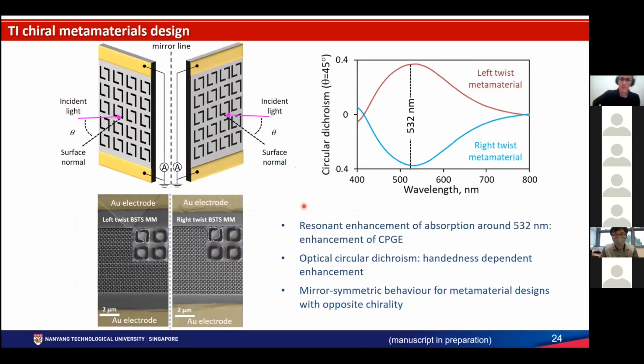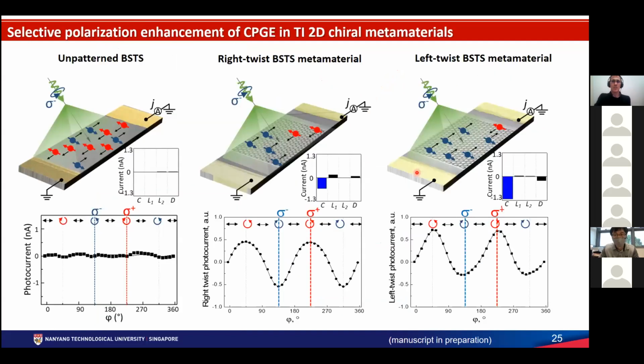So the following step was naturally to try to introduce some optical chirality. So we structured the material with two metamaterials with opposite twist, one left twist and one right twist, which, when you come at oblique incidence, in this case 45 degrees, show a very clear circular dichroism, which is mirror symmetric for the two kinds of metamaterials. And what we observe now is a very different picture. You see that in the structured pattern, we try to reduce now the effect of the thermoelectric contribution. So we try to set the photocurrent almost around zero.